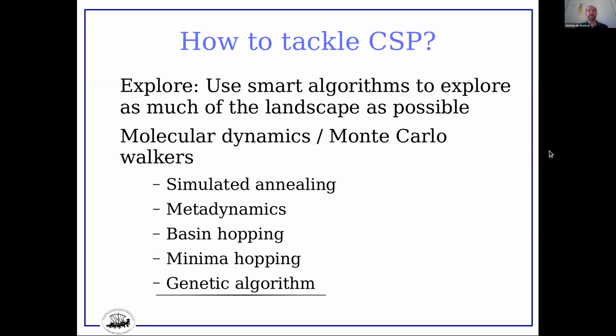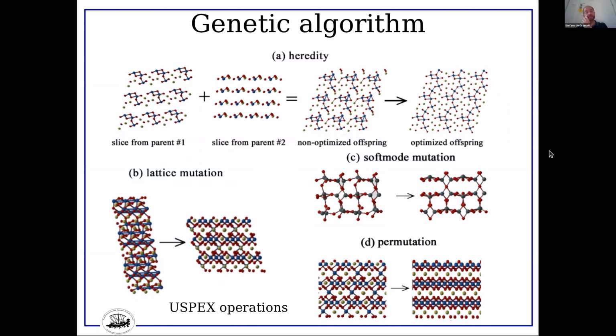So basically, what you do, you have a population of candidate structures, and then you rank them in terms of their energy or enthalpy, if you do things as a function of pressure. And then you need to generate new configurations. And these new configurations must be reasonable but diverse. There are various ways in which you can do this exploration. You can take two configurations, extract structural motifs from the two parent configurations and put them together, and then optimize the new structure, and so find a new optimized structure that may have some novelty.